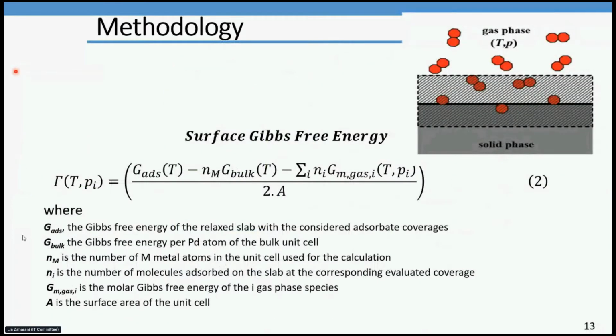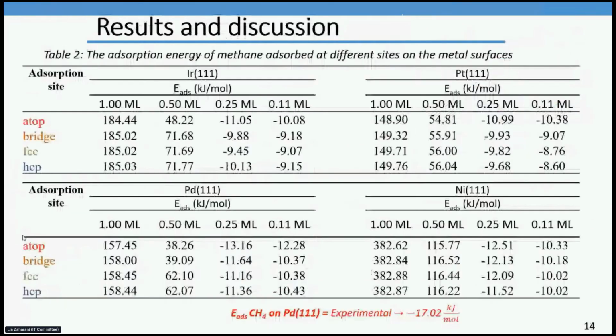Surface Gibbs free energy is used as a standard to test the stability of water and methane adsorbed systems under different conditions. It is determined using this equation 2, and the more negative the surface Gibbs free energy, the more stable the adsorbed structure. This table shows the adsorption energy of methane adsorbed at different sites on the metal surface at different coverage.